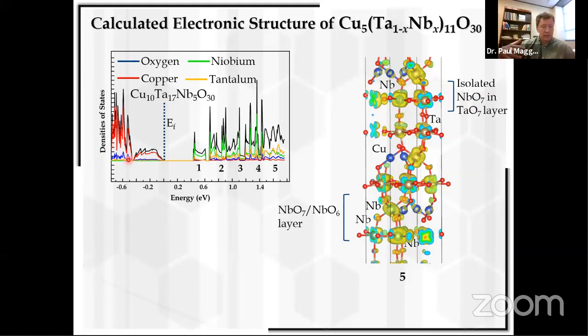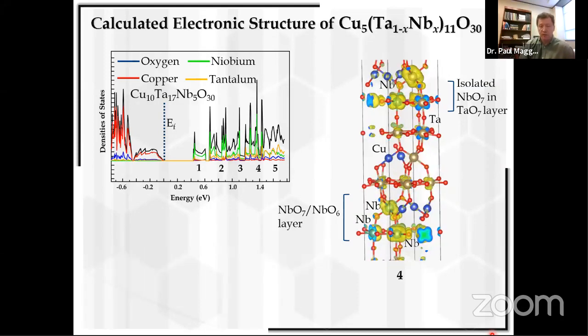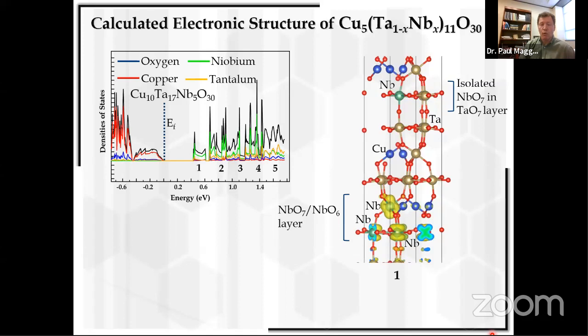No matter where those electrons are excited to, they rapidly thermalize to the bottom of the conduction band. So they rapidly thermalize to 1. So wherever those electrons are being excited to, they're going from 5 and then thermalizing very fast to 1. So those electrons are thermalizing to the extended parts of the network and not to the isolated parts of the network. They're not becoming trapped. The electrons are becoming delocalized, even though you've got a solid solution.